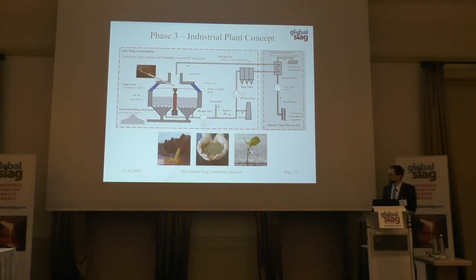Yes. Okay, which leads us on to the question, what is your specific energy consumption in terms of kilowatt hours per ton of granulated blast furnace slag? I don't have the value here, but I can tell you we currently have with this fan about 700-800 kilowatts of electrical power, which we need for 0.5 tons per minute of slag flow. So you can calculate the specific values out of these 2 parameters.